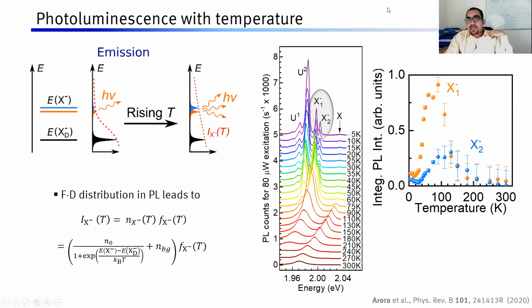Now the problem is we have been expecting that the intensity should just keep rising according to the Fermi-Dirac distribution. But why does it fall? Actually, the fall comes from another term, which is the oscillator strength, which is about how many photons are actually getting absorbed to create these trions. So this oscillator strength can be found just by measuring the absorption spectrum as a function of temperature. And if this oscillator strength falls very rapidly, then we will know that this fall can be explained. Because there are two terms multiplied: one is the population, one is the oscillator strength.